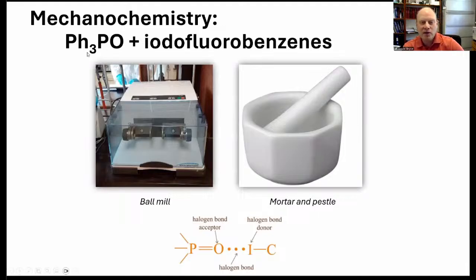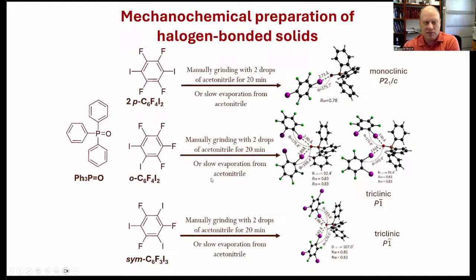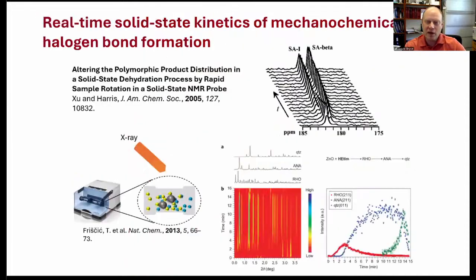So as a proof of principle, we were looking at the formation or what happens to this co-crystal between triphenylphosphine oxide and iodo-fluorobenzenes, and again, looking at a halogen bonded system. So to start, we've got our triphenylphosphine oxide and 3 different donor molecules here. And we're able to get single crystal structures using regular solution methods. And this is basically just to see what we have from the crystal structures. And then we try to monitor if we can make the same forms mechanochemically.